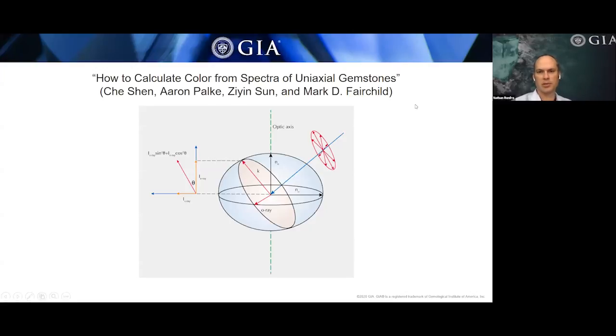And they also developed a formula to measure the component portions of the ordinary and extraordinary ray as the light travels through the mineral crystal at different angles. And so if you're not perpendicular to the optic axis, the ordinary ray and the extraordinary ray will have different relative component strengths. And so they developed this formula to be able to measure each contribution of the ordinary ray and the extraordinary ray, and that way they can predict the face-up color of the sample, as long as they have the polarized spectra measured and they have the angle that the light entered the crystal relative to the optic axis, as long as that's known.